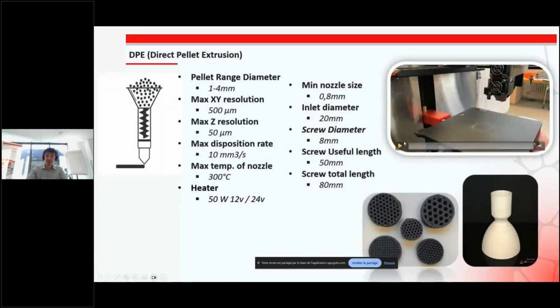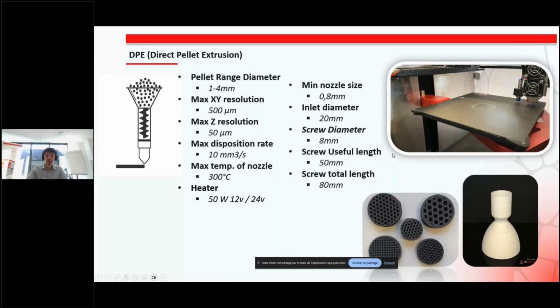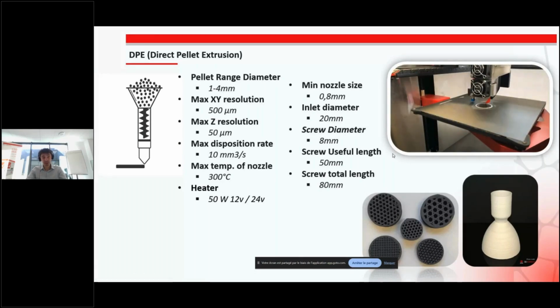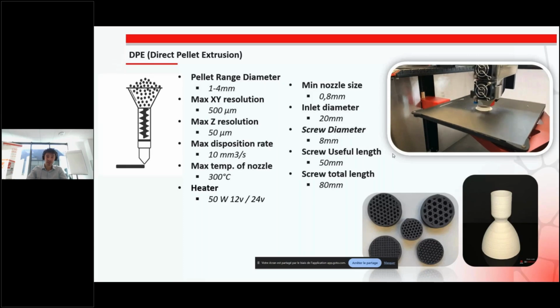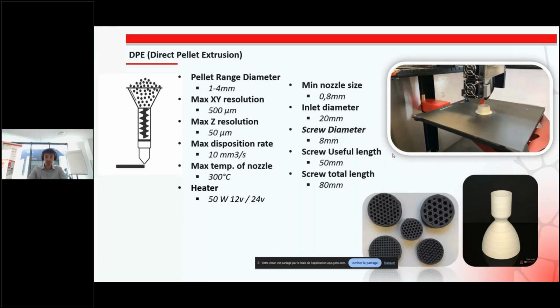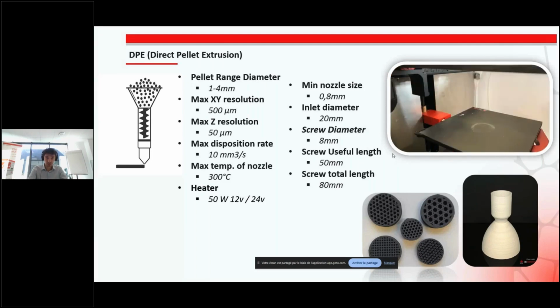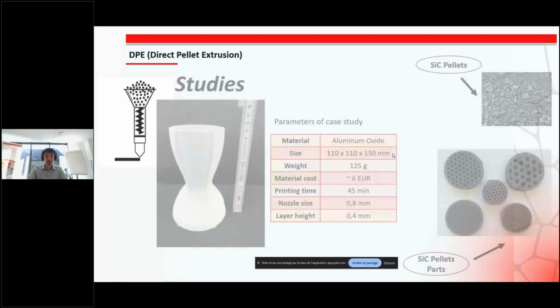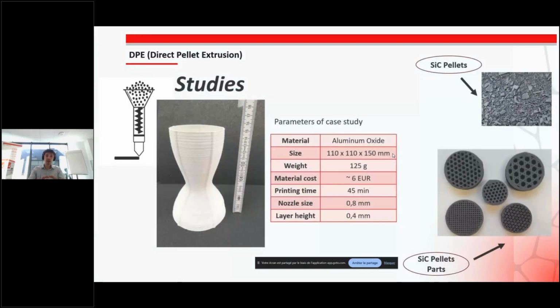Another process is direct pellet extrusion. So the material is not a filament, not a paste, it is pellet. The same pellet already used for the ceramic injection molding process, and it's possible to print parts with a direct pellet extrusion head. One of the main advantages of this process is that it's a very fast, very quick process. For instance, to print this part with direct pellet extrusion, quite a big part, you can see the size of the part is 110 by 110 by 150 mm. The printing time is 45 minutes.